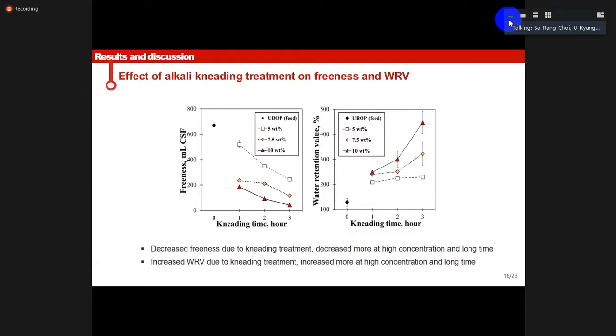This slide shows the effect of kneading treatment on freeness and WRV. The graph on the left shows the freeness of the fiber by kneading time and pulp concentration. Control is shown in black dot, white is 5, yellow is 7.5, and red is about 10% of pulp concentration. The higher the concentration and the longer the time, the more the freeness decreased.